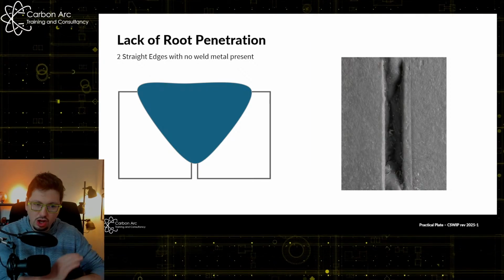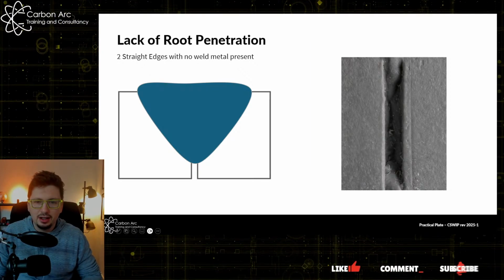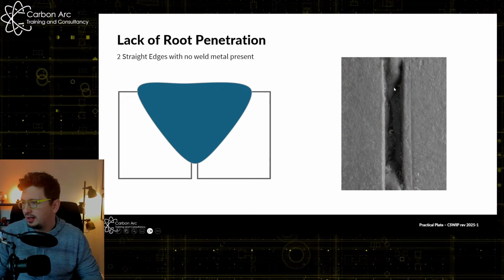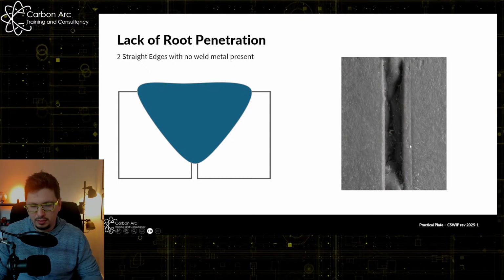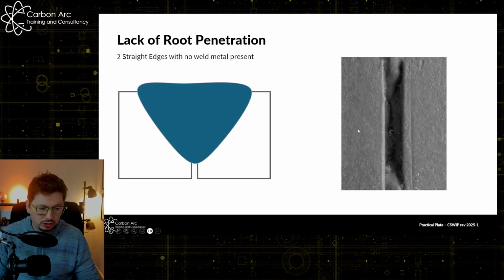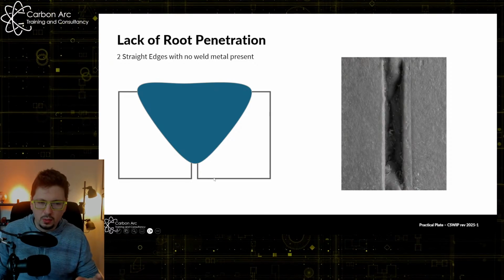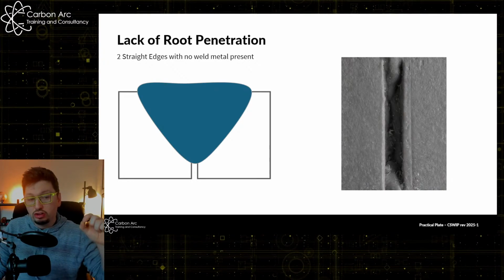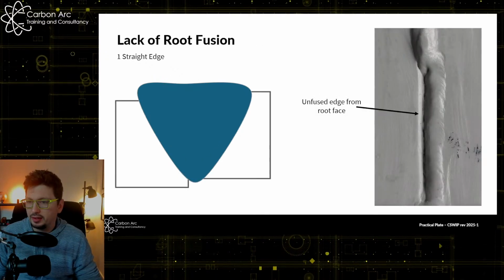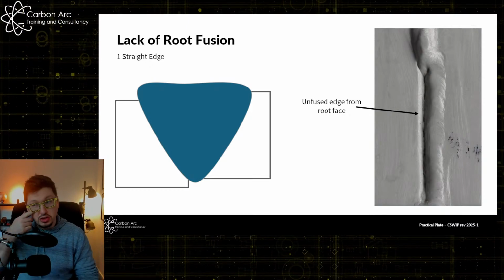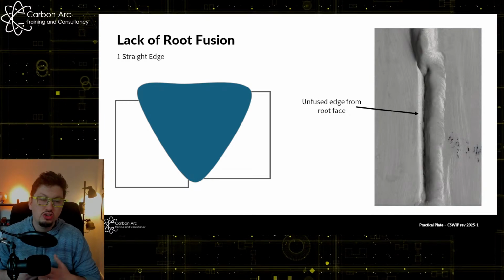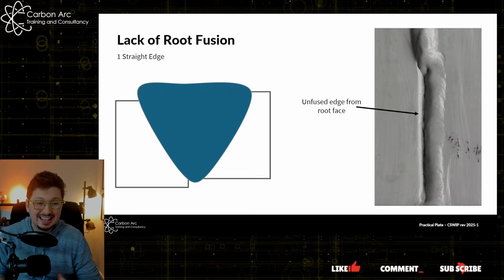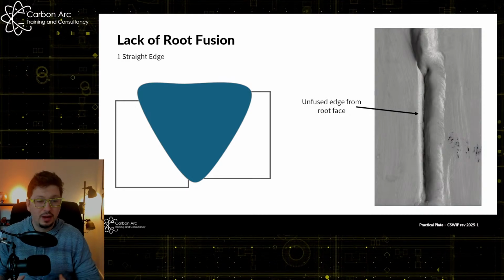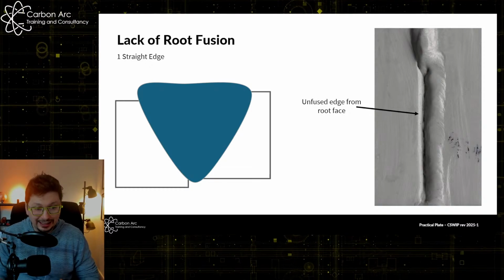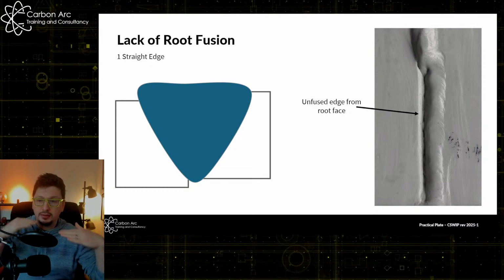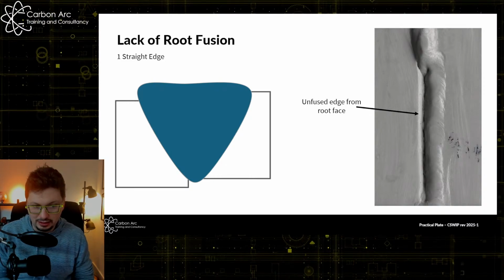2 straight edges, no weld metal. So we can see here we've got our 2 very defined edges coming down from our prep. Okay, so our root face hasn't been touched. Lack of pen, generally caused by too low of an amperage or too thick of a root face. Okay. Then we have lack of root fusion. So this is 1 straight edge. Normally occurring where we have misalignment of the plates. So if you're given a sample where you can see a high amount of linear misalignment, so the plates are physically stepped out from each other, have a look to see if you've got this defect.